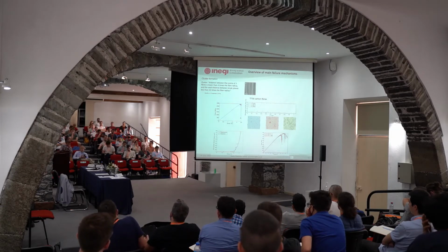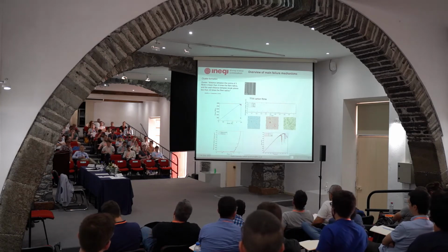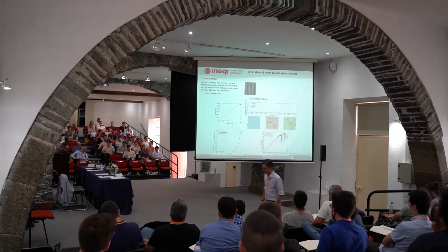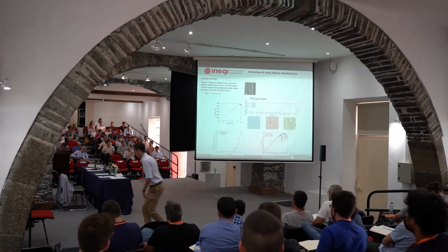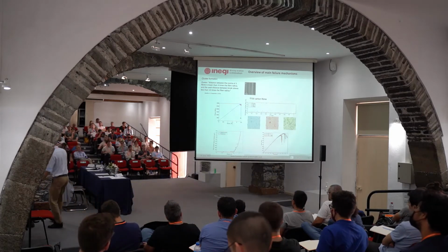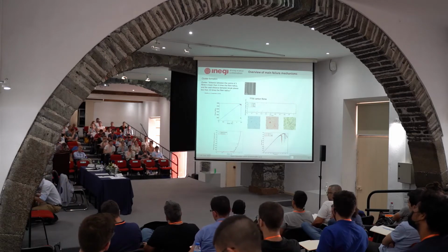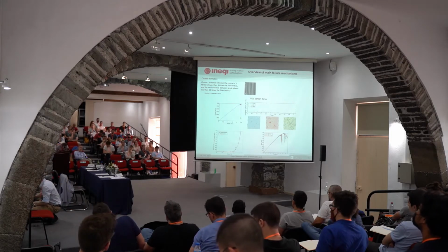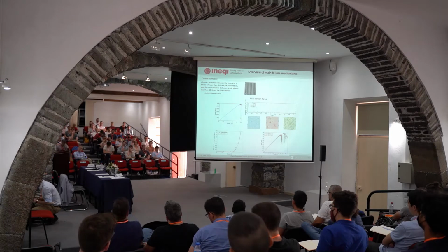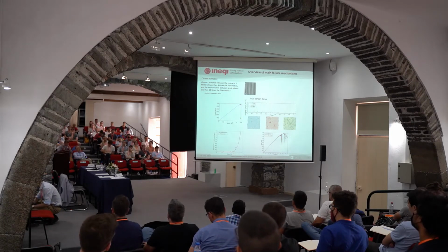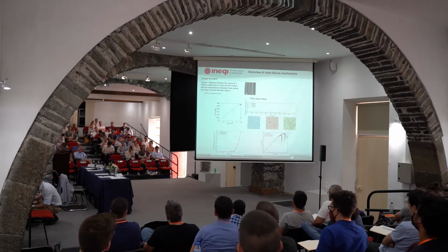But before performing the hybridization, we ran simulations, and we actually use models to optimize the microstructure. So we can optimize, say, the fiber volume fraction between the different types of fibers and resin, of course. But for that, you need these models, okay? And you can perform parametric analysis, see what happens if you change the shear modulus of the resin, what happens if you change fiber A to fiber B, and so forth. Okay, so we can study.